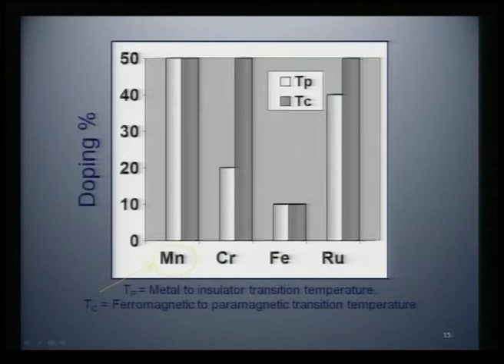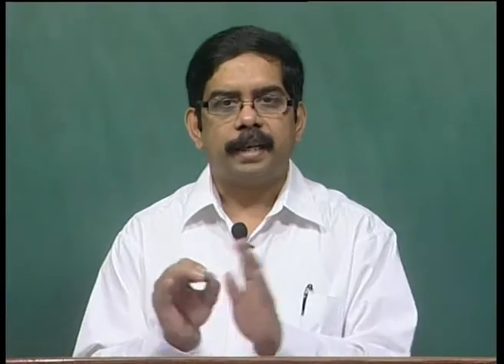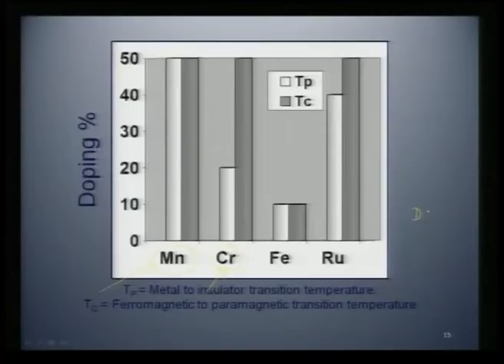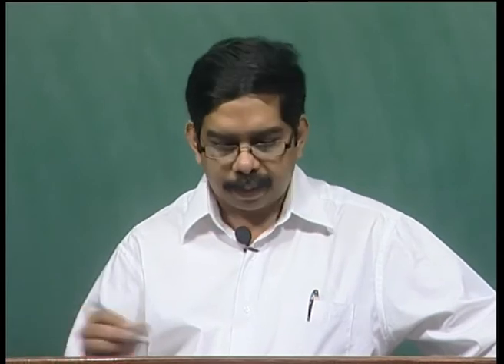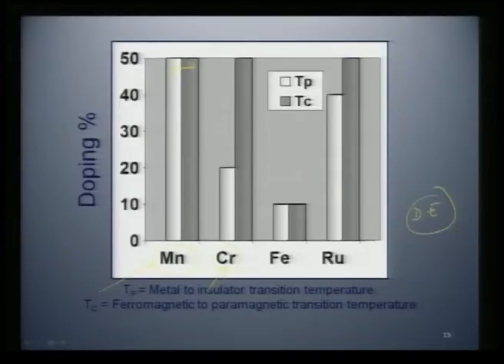But if you substitute chromium in the site of manganese, you can see that the metal insulator transition is happening up to 20%, although the ferromagnetic transition is still there up to 50%. This is a very strange thing, that you can see ferromagnetism equally strong up to 50% of chromium, whereas the metal insulator transition deviates. But the real signature for a double exchange mediated ferromagnetism is that both the TC and TP, or the metal insulator transition, have to coexist like this if it is truly mediated by a double exchange model. But this is not happening in chromium. And if you see iron, as I showed you in the previous slide, both are killed at around 12%.